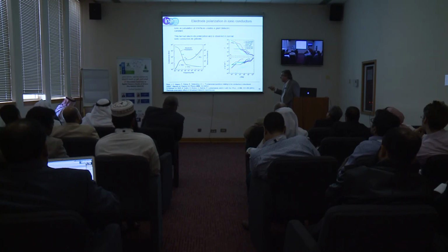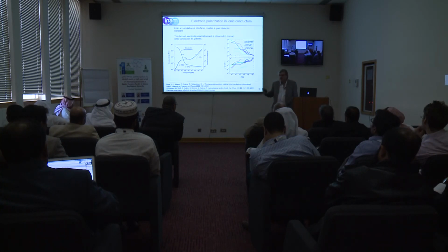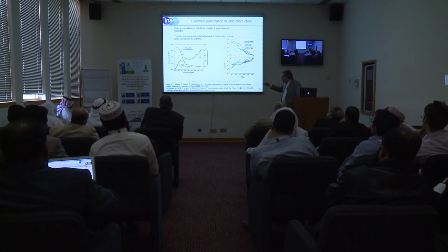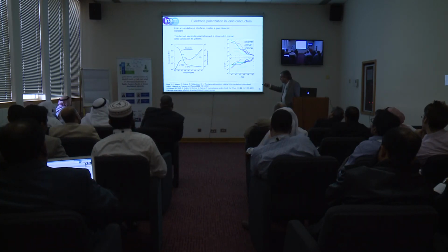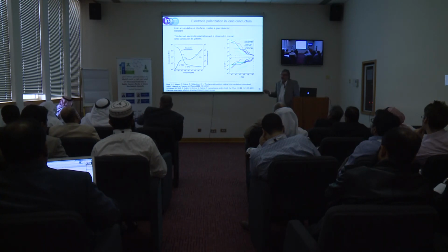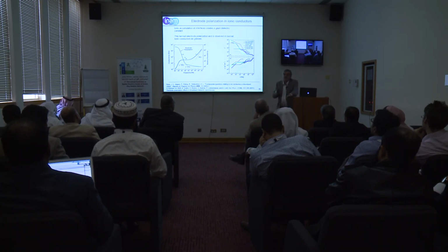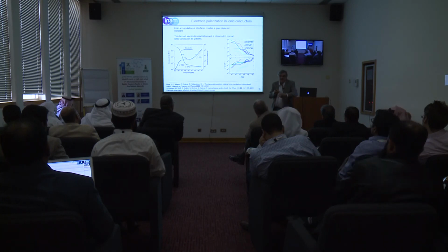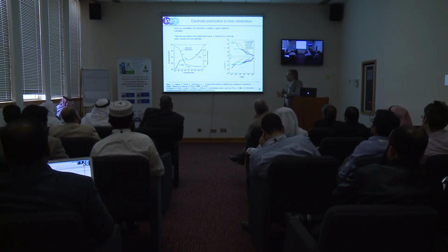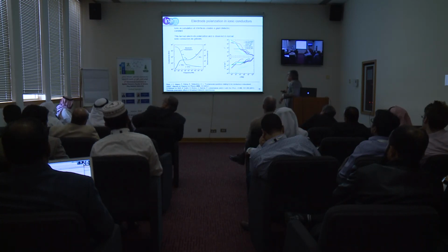But when we go to very low frequency, this has to disappear, as I said before, because this is ionic conduction, and you cannot have DC ionic conduction. It's impossible, okay? It goes away. When the conductivity goes away at low frequency, the polarization goes up. And this is because you are building up ionic charge close to the electrode, not very different from electrochemical capacitance. You remember the double layer capacitance and Gouy-Chapman, all these things with ions. In the solid it is the same thing. So this goes quite big.